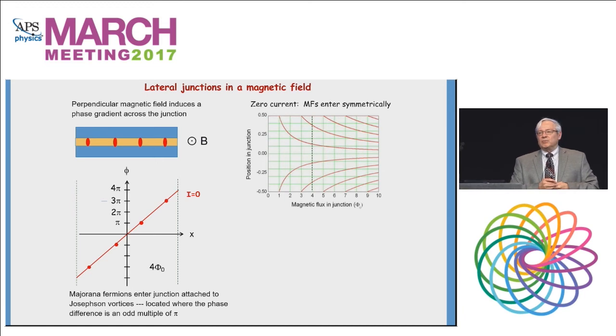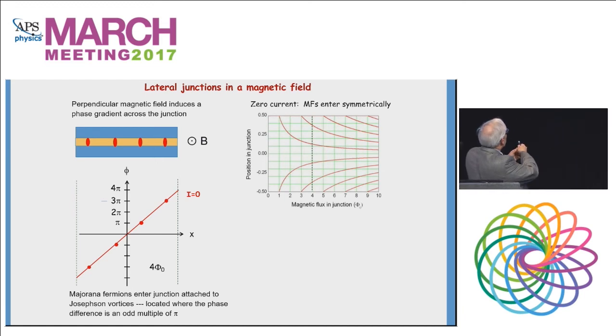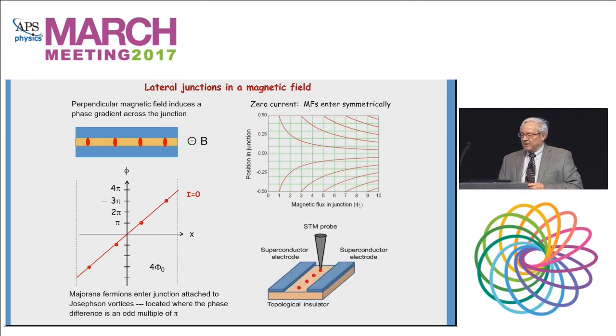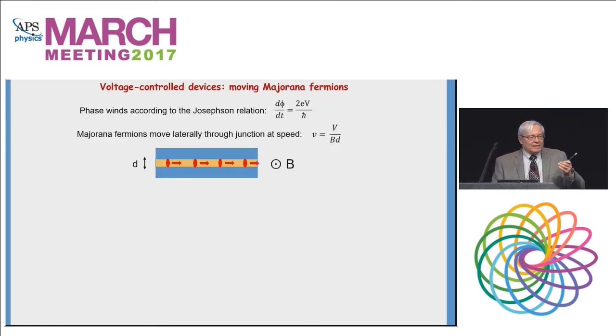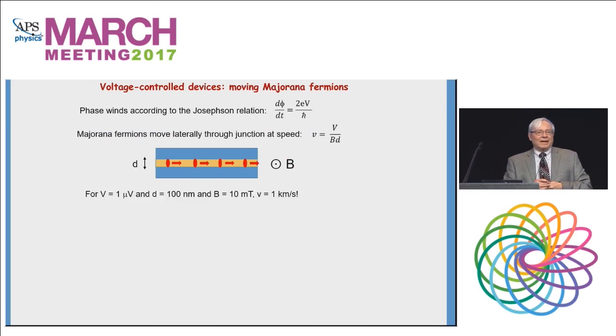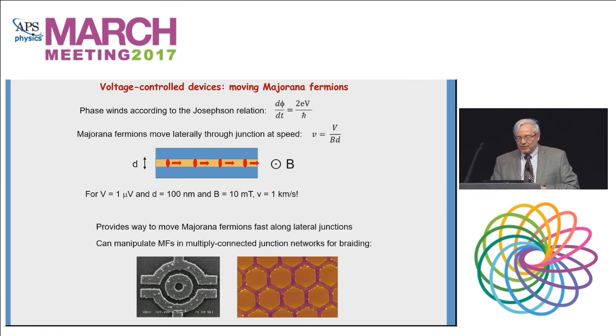The system we're interested in is when you apply a magnetic field and these Majorana fermions become localized in the junction. They enter the junctions just like vortices in a superconductor. And you can imagine experiments where you scan along the top. We're trying to do this and actually detect the zero bias states from these Majorana fermions. We like this system because you can actually move the fermions. When you apply a voltage, the phase winds very quickly. You can move them around something like 1 kilometer per second, very fast. And you can imagine devices in which you can move them around and braid and do various kinds of nice experiments.